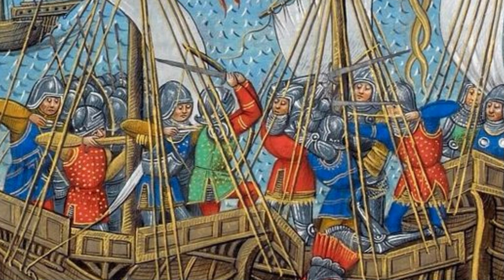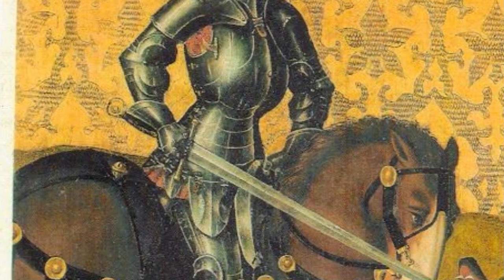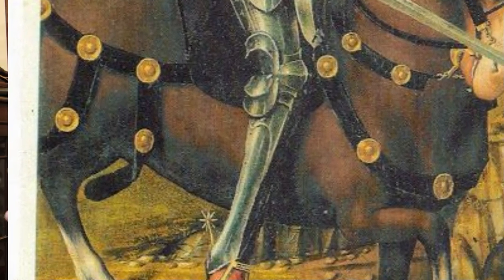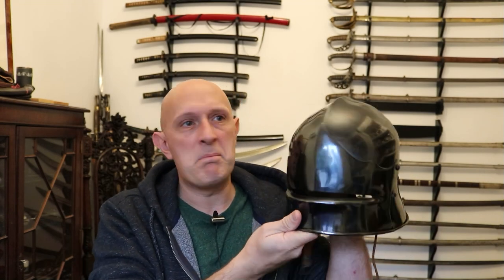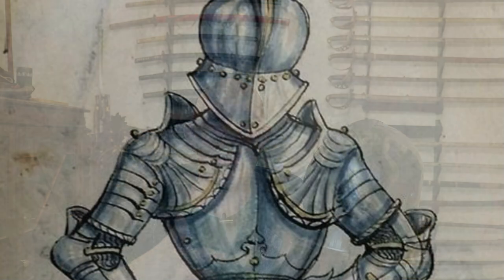People often fixate when doing tests on penetrating things like helmets or breastplates. It has to be said right off the bat that there is a huge variety in armor within a suit — and between different people — in terms of steel quality, whether it's steel or iron, whether it's heat treated, and the thickness. So essentially both the material and the thickness differ. Even within a top-quality late 15th-century harness from Germany or Italy, you have varying thicknesses: the front of a helmet or breastplate might be around three millimeters thick, while a greave might be only 0.8 of a millimeter — hugely different.